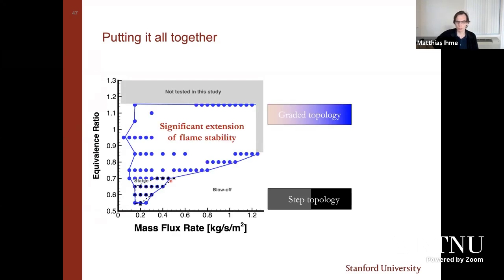By utilizing this continuously graded system, you're seeing that we can significantly extend the operability to extremely high mass flow rates. We had to cut off at some point simply because our mass flow controllers were maxed out. But overall, you're seeing that this graded topology in conjunction with additive manufacturing processes allows us to tune the performance and at the same time get an extended operability of the porous media burner.